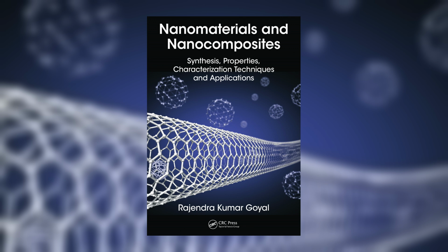Direct methods, SEM, TEM, and SPM magnify past the eye and read the size off an image. Indirect methods, XRD, and the spectroscopies never see the particle at all. They exploit a law that ties behavior to scale. The canonical inversion is this. A finite crystal has too few lattice planes to fully cancel off Bragg intensity, so its diffraction peak broadens inversely with crystallite size. Characterization is measurement by inference. Every technique trades what it resolves against what it must assume in order to invert.